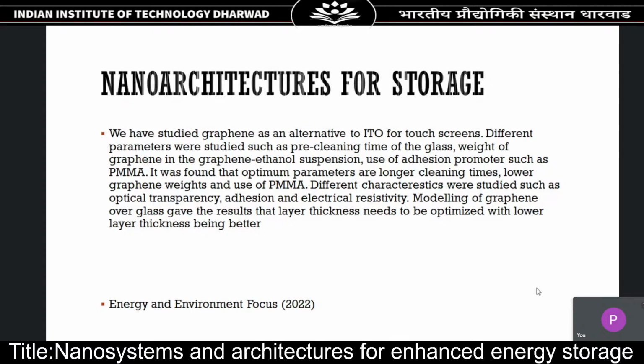So one of the things we thought was, instead of indium tin oxide for the touch screen, we can use graphene. So we have very different parameters of the graphene. We have taken glass, then we have done some pre-cleaning. We have also varied the weight of graphene in the graphene-ethanol suspension. We have used an adhesion promoter such as polymethyl methacrylate, and we have found some optimum parameters, which are nothing but longer cleaning times, lower graphene weight, and the use of PMMA. And we have studied different characteristics such as optical transparency, adhesion, electrical resistivity, and some modeling was also done. So this was also recently published.